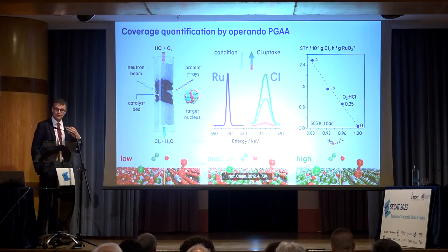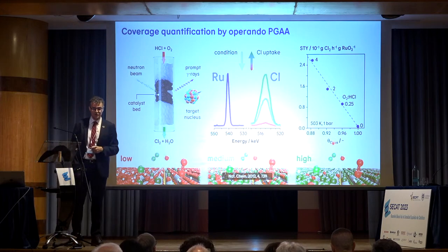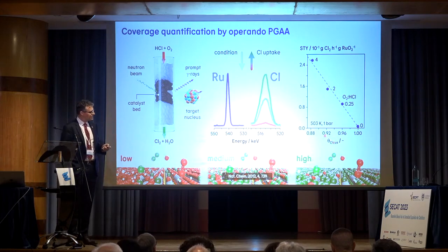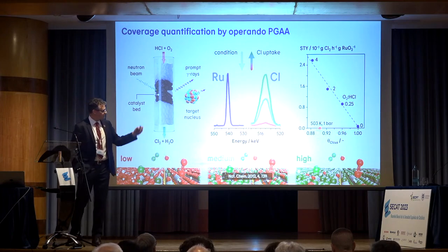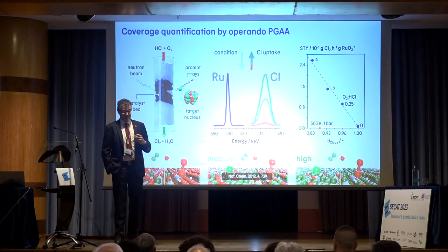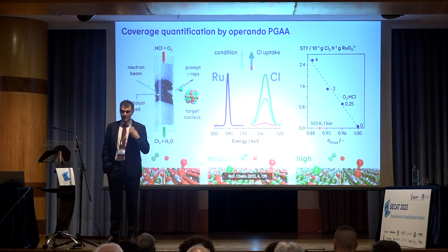So this was a determination of coverage of chlorine under reaction conditions. And we could see that surfaces of ruthenium oxides are largely covered by chlorine, in some cases between 88 and 100% of chlorine, already indicating that the rate limiting step of this reaction is the evacuation, the removal of chlorine from the catalytic surface. Well, this technique, it's not very common to develop techniques to measure at ambient pressure on polycrystalline materials under operating conditions coverage of a species.